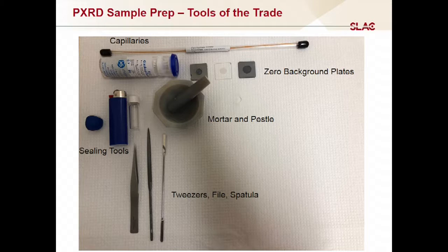So a couple of other tools, a mortar and pestle. This is great for grinding up your sample, or if you want to mix different powders together, this is a good way to do it to make sure you get a good homogeneous mixture of the powders. In order to seal, I'm going to talk about using, this is just some modeling clay, and this is just a regular Bic lighter. You can use both of these to seal the capillaries, not the lighter for the Kapton. It doesn't really melt. But for the glass ones, you can use a lighter.